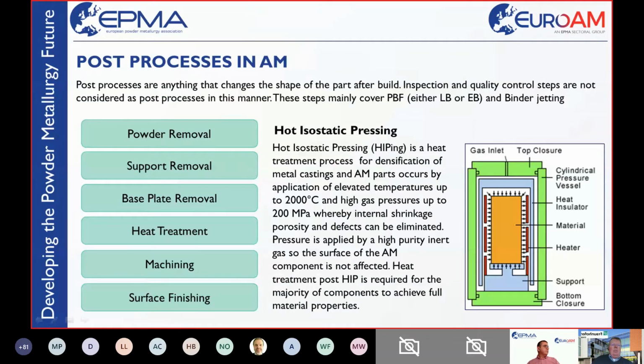Again, post-processing, so powder removal, support, base plate, heat treatment, machining, surface, as said before. One special thing is the hipping, and hipping means hot isostatic pressing, which is still done with a lot of 3D printed products. As I mentioned at the very start of this presentation, we have in many processes a certain amount of statistically distributed closed porosity, and with closed porosity, hipping would be the right post-processing step to get rid of that. Open porosity at the surface can't be solved with hipping, of course, but hipping is used by very many manufacturers, therefore it's mentioned here.